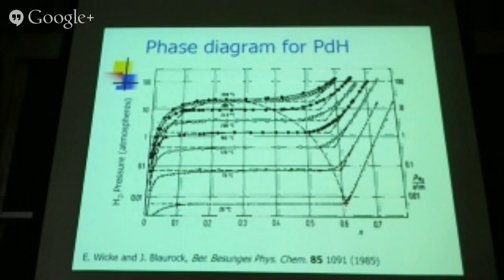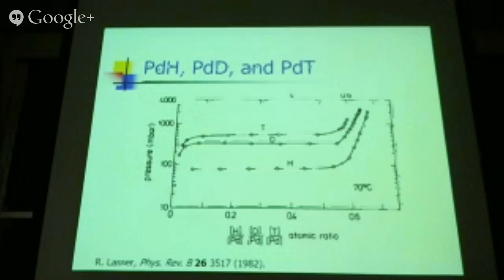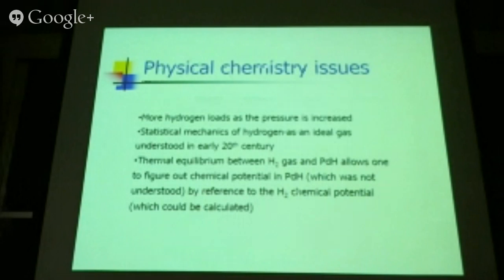And then once you reach the edge of the miscibility gap, you go up. So you have to add more and more pressure, and it's logarithmic. So you need a factor of 10, and another factor of 10, and another factor of 10 to get the loading to go up. So this is telling you that it's harder and harder and harder to get high loading. That tells you there's a really good reason why people have trouble getting the high loading needed. If you change hydrogen to deuterium to tritium, you get a change. And this effect has to do with the zero-point energies. It's nothing particularly special about the different elements. It's physical chemistry issues.